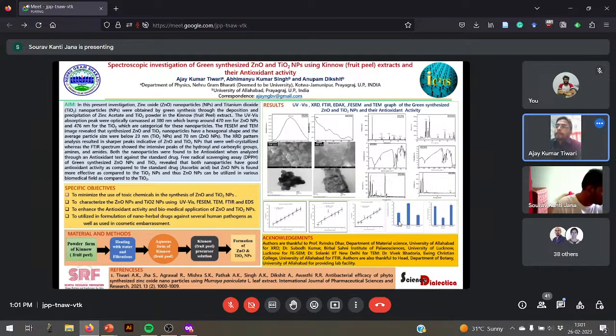The FESEM and TEM images reveal that the synthesized zinc oxide nanoparticle and titanium dioxide nanoparticle have a hexagonal shape, and the average particle size was below 23 nanometer for the titanium dioxide and 17 nanometer for the zinc oxide. The XRD also resulted in sharper peaks, indicating the zinc oxide nanoparticle and titanium dioxide nanoparticle were well crystallized, whereas the FTIR spectrum showed intensive peaks of the hydroxyl and carboxyl group, amine and amide.